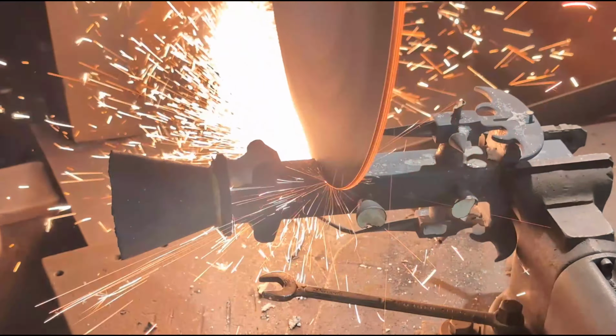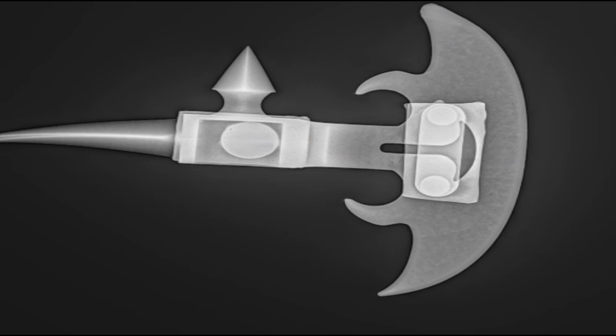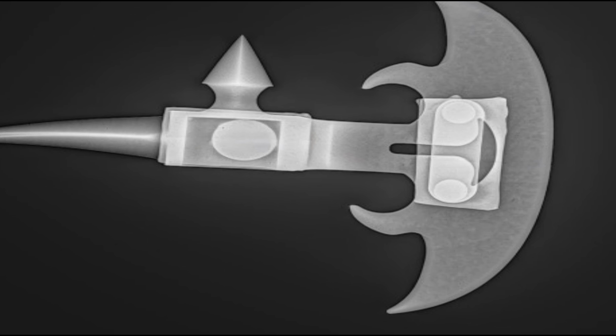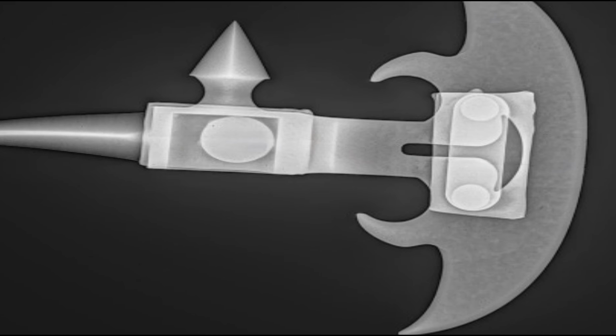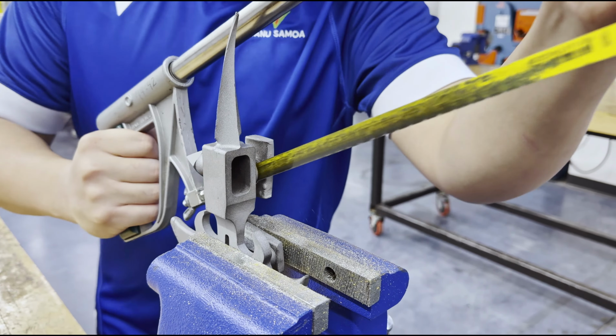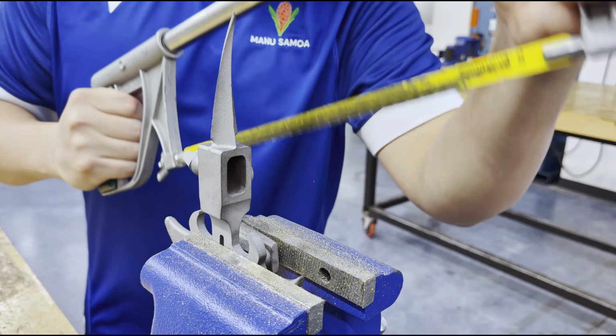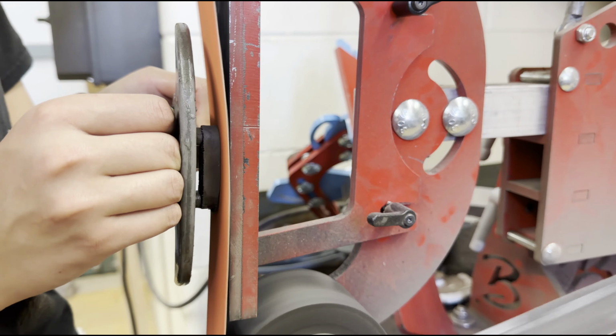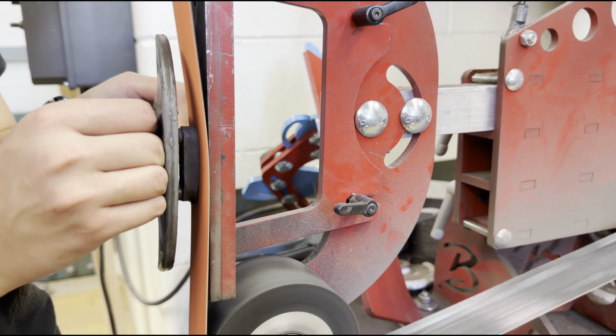After this initial separation, non-destructive testing was performed using X-ray imaging to evaluate the internal integrity of these castings. Once internal quality was verified, the remaining gates were removed and the castings underwent initial grinding and surface refinement.